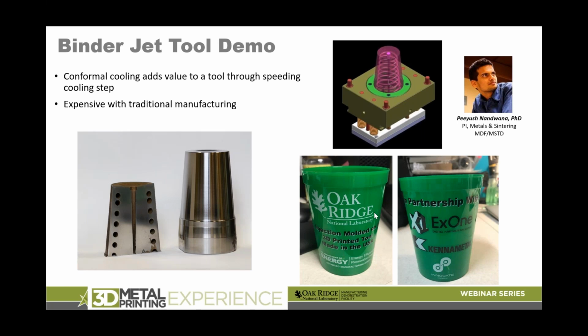But what was most exciting about this demonstration was we realized just how cheap binder jetting can be compared to laser. Laser makes a lot of sense for aerospace, medical, and these really high-end applications. We're talking about tooling or mass production where you have very small profit margins, small liabilities too, and then you need something more price effective. So we got this tool quoted for laser. Just the print itself was $15,000. For binder jetting though, the whole part being made and machined was less than $1,000. It's over an order of magnitude cheaper than laser. And I think a lot of people are catching on to that and looking more closely into binder jet.